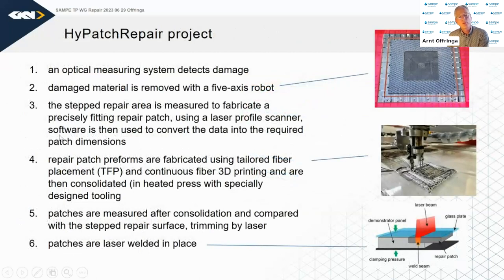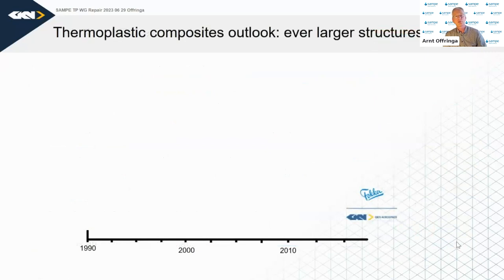So first of all, there's an optical system detecting the damage itself. The damaged material is removed with a five-axis robot. The repair area is measured, and that's used to fabricate a repair patch. And that's a 3D made repair patch. And that repair patch is then subsequently laser welded into the damaged area. Now, this first research project has been concluded, and there's a second one ongoing to achieve further results. But there's still work to be done.